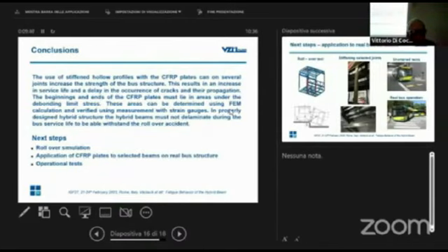So conclusions: the use of stiffened hollow profiles with CFRP plates can on several joints increase the strength of the bus structure. This results in an increase in service life and a delay in the occurrence of cracks and their propagation. The beginnings and ends of the CFRP plates must lie in areas under the debonding limit stress. These areas can be determined using FEM calculation and verified using measurements with strain gauges.